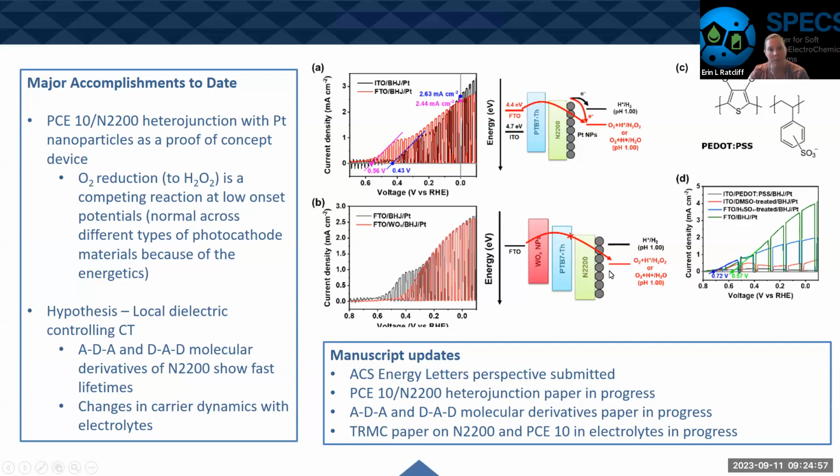But in organics, we're probably going to be extra concerned about that because oxygen reduction in water results in hydrogen peroxide, and hydrogen peroxide evolution is going to have some major consequences on the chemical stability of our films. Conventionally, this is because oxygen always dissolves in water. This is a problem regardless of the material that you use for your photocathode.